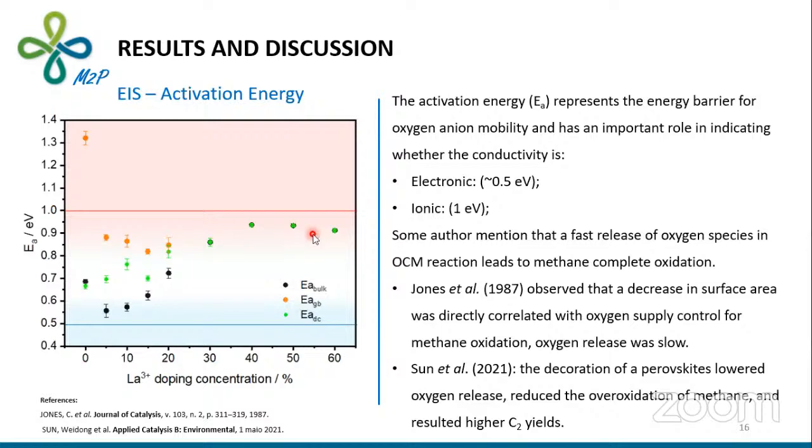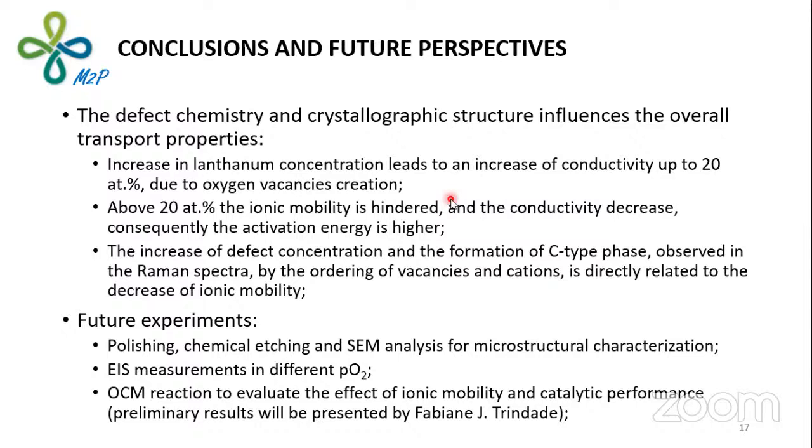Well, so we can conclude that there is a direct relation between defect chemistry, crystalline structure, and ionic conductivity. The increase in lanthanum concentration increased the ionic conductivity up to 20%. And above that, the ionic mobility is hindered due to the increase of oxygen vacancy concentration and the emergence of